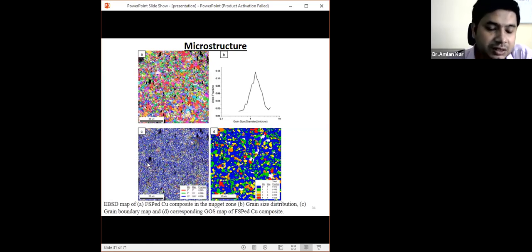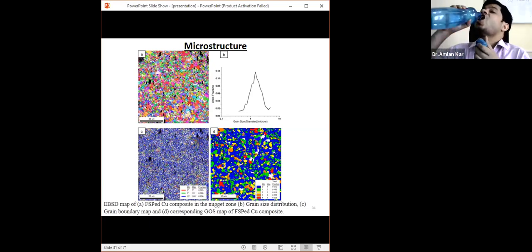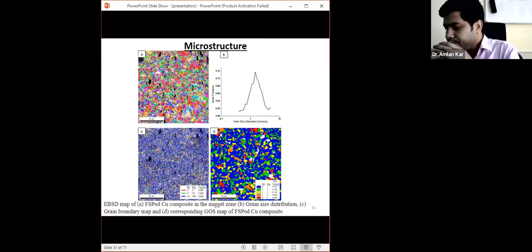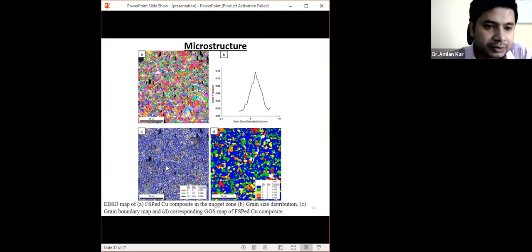And you can see there are different types of grain boundary here. There are three kinds of grain boundary visible. One is subgrain boundary, low angle grain boundary, and high angle grain boundary. So depending on the color, you can find out what kind of grain boundary has developed during the process. From there, you can easily find out that 80% of the grains are surrounded by high angle grain boundary, which is represented with the help of blue color here. So since the material is surrounded by high angle grain boundary, that means it is a recrystallized microstructure.